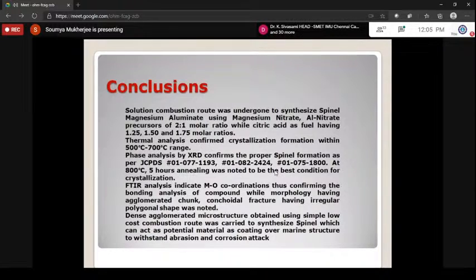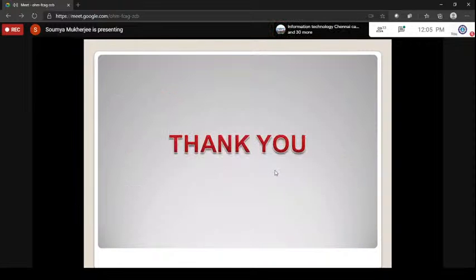FTIR analysis indicates our metal oxygen coordination, that is the chemistry part, where we are getting all these analyses, while morphology is supported from the same, where we are getting a very dense structure, agglomerated chunk structure. And this dense structure gives an indication that it is very good for mechanical properties and also corrosion resistance. Thank you.